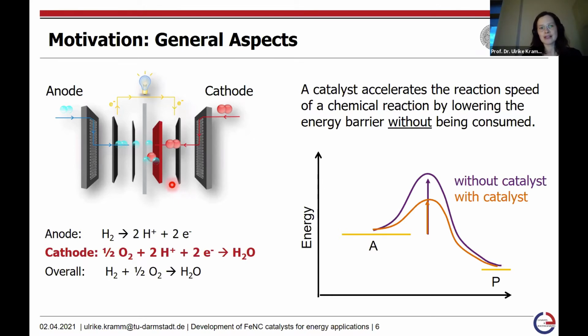So the catalyst accelerates the chemical reaction, and based on that we can gain sufficient energy out of the system. What is shown here are the bipolar plates with the gas channels in order to transport the hydrogen or the oxygen to the catalyst layers. These are the catalyst layers, and to get a fine and nice distribution, there are also some gas diffusion electrodes that enable a better transport of the gases to the overall catalyst layer.